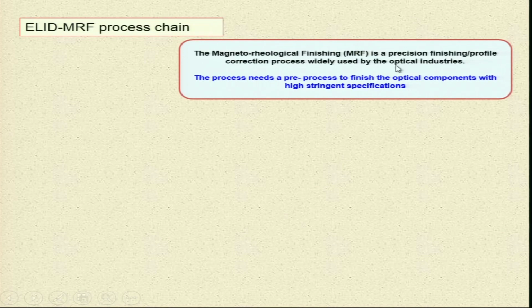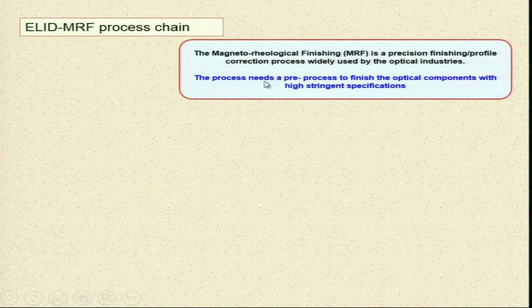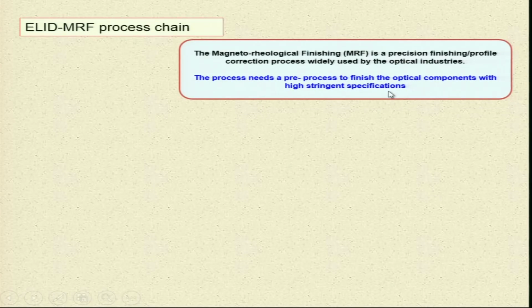industry, because there you need very fine surface finish, maybe even less than 1 nanometer, and there you use this chain, ELID MRF chain, and you know this ELID MRF becomes a hybrid process. ELID itself is a hybrid process. By adding the MRF process you further hybridize it, because you have 3 processes: grinding, the electrochemical process and the MRF process. The process needs a pre-process to finish the optical components with high stringent specifications.